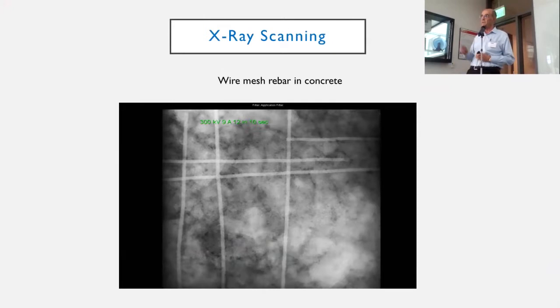The way it works is it's got a needle, and when the needle goes up to a maximum location on the scale and comes back, at the maximum point, that is where your rebar is. So as you scan along a slab, it goes up, and then just before it comes down, you know where that rebar is. And we're also talking about two senses, the X and the Y direction. So even with GPR, which I forgot to mention, we're talking about X and Y direction. You scan in both directions. You can't pick up both the X and the Y at the same time. The intensity only comes in unidirectional.